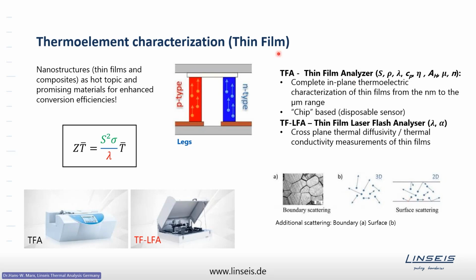The instruments which are used for the characterization of thin films are the so-called thin film analyzer. It's a complete measuring platform using disposable sensors on which a thin film is deposited. Then this disposable sensor with a film on it is placed in the analyzer, and depending on the configuration of the analyzer, you can characterize the Seebeck coefficient, electric and thermal conductivity, the heat capacity, the Hall constant, charge carrier concentration, and mobility.